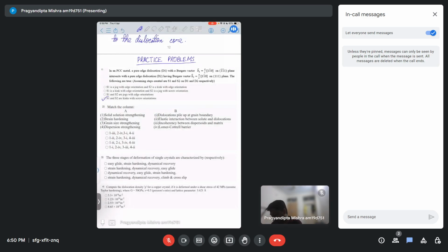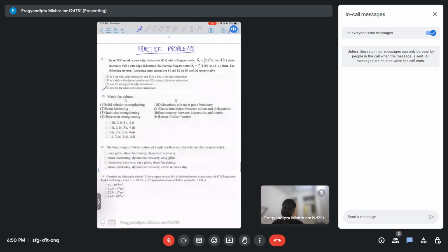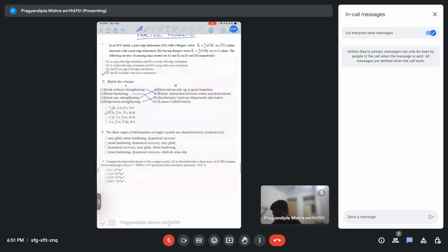Okay, second question, match the following columns. Solid solution strengthening. So what does solid solution strengthening lead to? It leads to elastic interaction between solute and dislocation. So we can match this, right? Strain hardening. Strain hardening will lead to what? Lomer-Cottrell barrier. Okay. Then grain size strengthening will lead to dislocation pile up at the grain boundary. And dispersion strengthening will lead to incoherency between dispersoids and matrix. So 1 is 2, 2 is 4, 3 is 1 and 4 is 3. So this is the correct option.